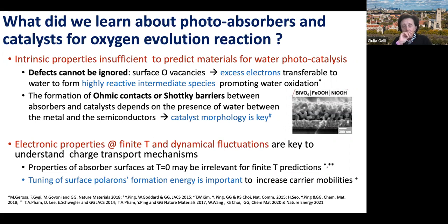I showed you a specific example of tungsten oxide to tell you that electronic properties at finite temperature and dynamical fluctuation are key to understanding charge transport mechanism. And there are several examples where properties of absorber surfaces at T equals zero may just be irrelevant for finite temperature prediction. Because again, the fluctuation and what happens at finite temperature is different, and this is very important to determining your chemical reaction. So basically, the interface is still the device, and defects are very important.